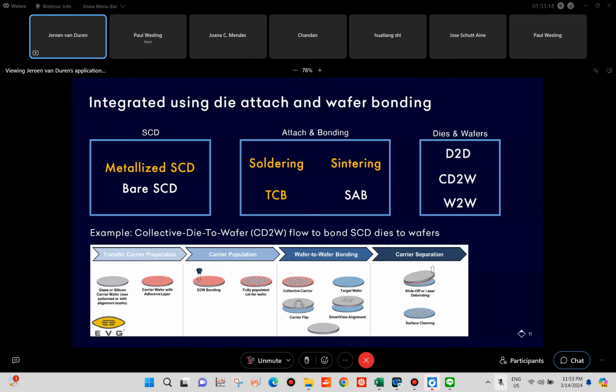dies and dies. So basically, you can do die-to-die bonding. You can do collective die to wafer bonding and wafer to wafer bonding. To explain a little bit on collective die to wafer bonding, shown here in the bottom from EVG. So what is done basically is the diamond dies are placed on a carrier, and subsequently this carrier that's populated goes into a wafer bonder together with the target wafer, and subsequently you permanently bond the diamond to the target wafer, and after that you remove this temporary carrier, and basically the diamonds have been transferred and permanently bonded to the target wafer. So that's an example of collective die to wafer bonding.